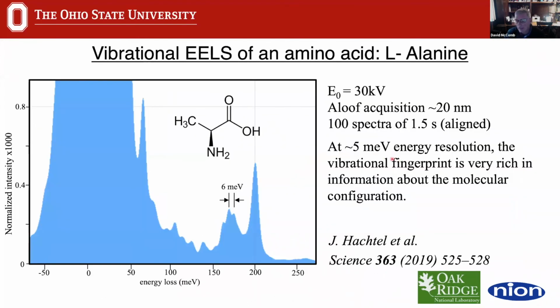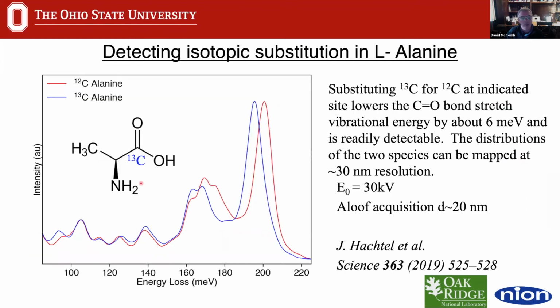And then Jordan Hachtel and the team at Oak Ridge then extended that further by looking here, for example, at L-alanine, very low energy spectrum, looking at that vibrational spectrum. What they did was a very obvious thing for a chemist to do, which is, well, let's take this carboxylic acid group and do some isotopic substitution, in this case with the carbon-13. And here you see the spectrum that you're able to acquire with the EELS from the carbon-12 and the carbon-13. So we're able to see that shift of the C double bond O stretch because of the isotopic change. And these two examples from Klie and Hachtel are really the first time that we've ever been able to detect isotopes using any technique in the electron microscope. And so this really opens up many, many opportunities, especially in biological systems. So I think this is a really exciting development.